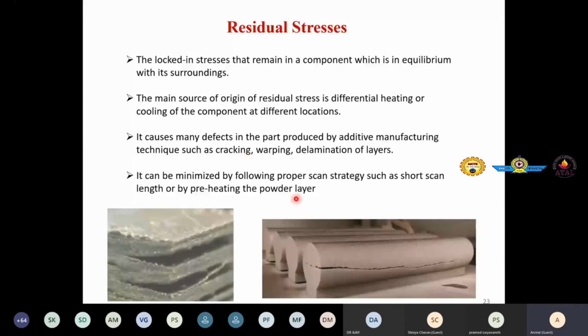And it can be minimized by following a proper scan strategy, such as short scan length, or by preheating the powder layer, or by some post-printing methods like heat treatment. You can see that because of residual stresses, some layers are spread apart and delamination is happening. In this figure, cracking is happening.